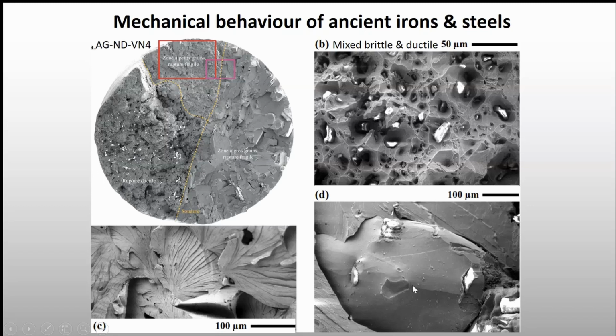Fragile with typical pattern, which is probably due here to the presence of phosphorus inside the matrix, and which embrittles the iron, but also the ductile fractures, which is usually predominant in the other samples, which forms itself around the slag inclusions that you can see here, and which provides some crack points once the material starts to be elongated. So the role of these slag inclusions in the fractures is important. So that is for the mechanical behavior of this material.